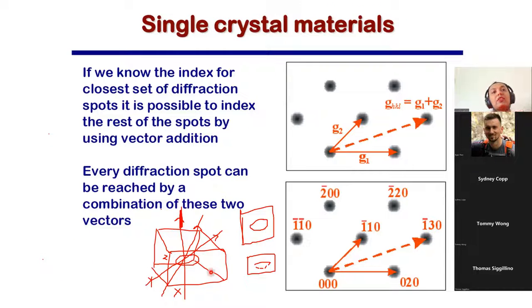So this was your crystal, and the loop that I showed you, an open loop, is exactly you are looking in the same direction. And once you get into microscopy, you will see that a zone axis is basically the direction of your eye. It is the direction from which your eye is looking; it is the same direction your zone axis is present. And once you have the photo of your zone axis, or your diffraction pattern of your zone axis, it would simply tell you, if this is your zone axis and these are your different planes, each family of planes is here. So it will give you the complete representation of G's along the zone axis.